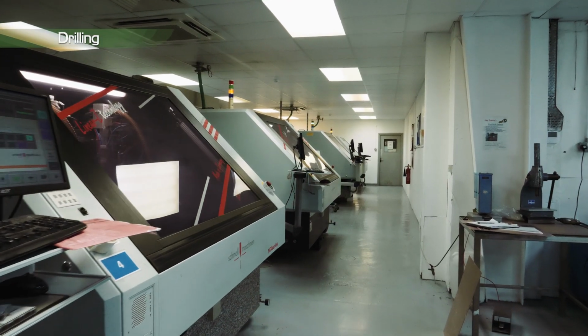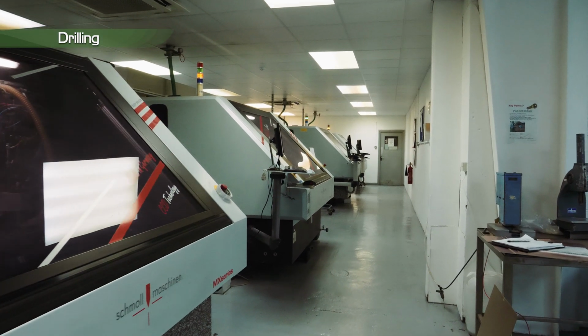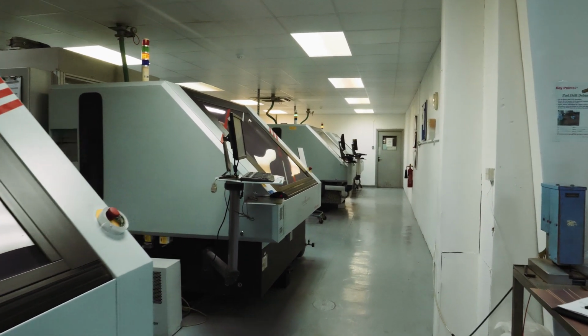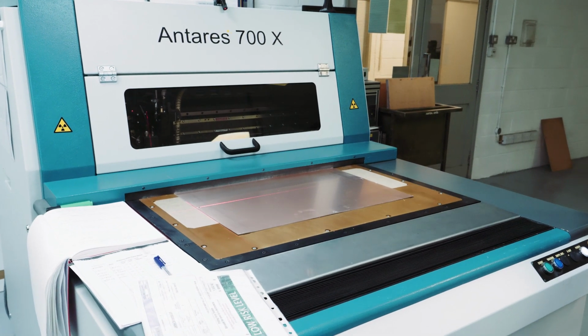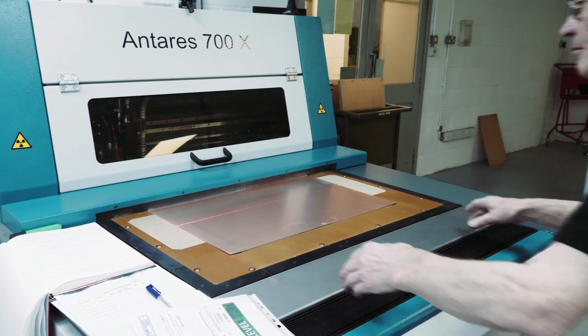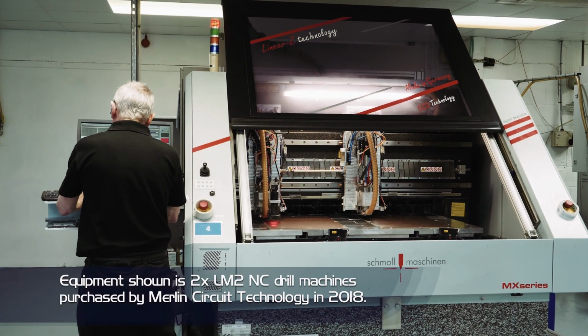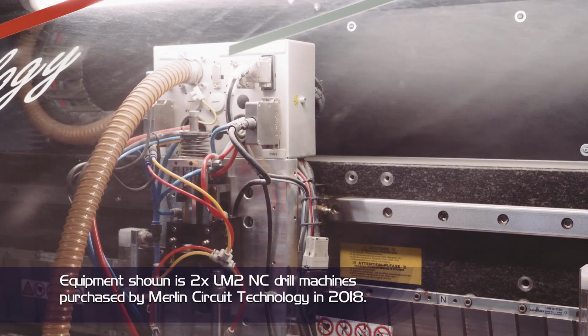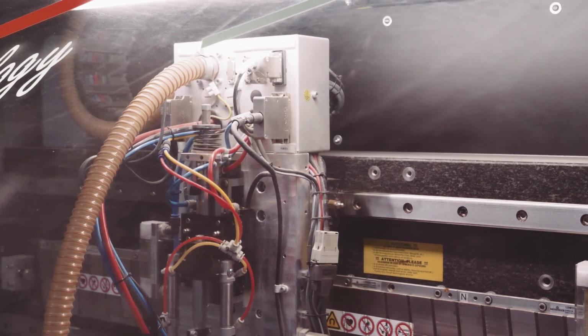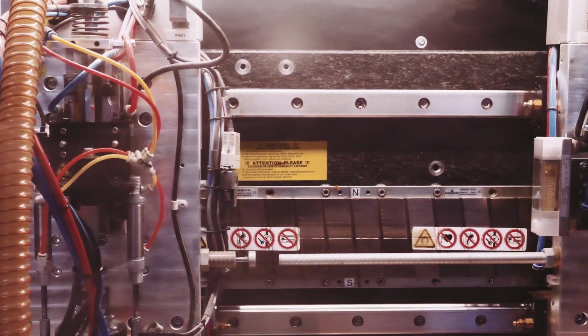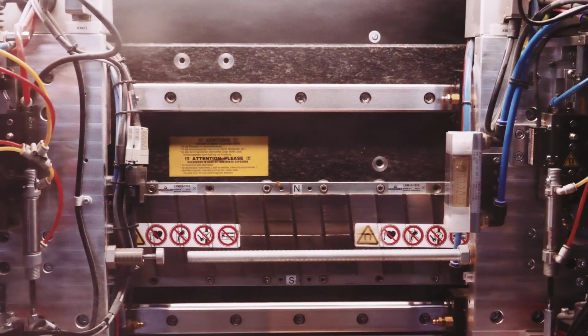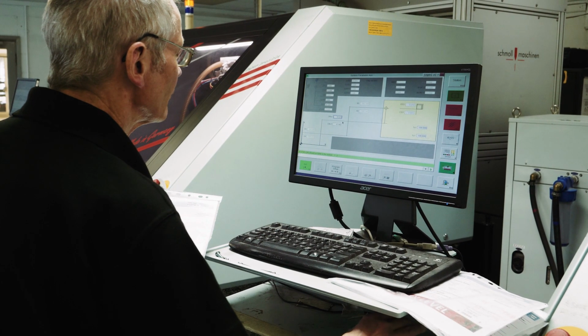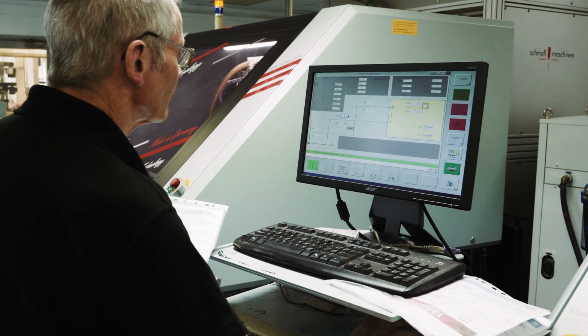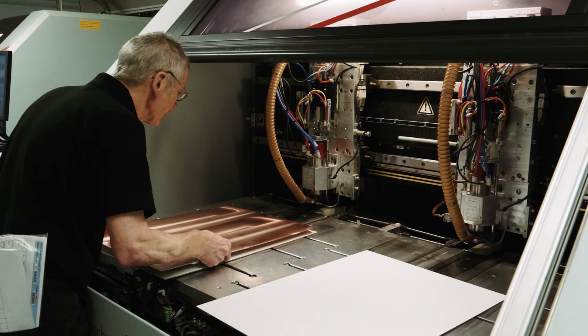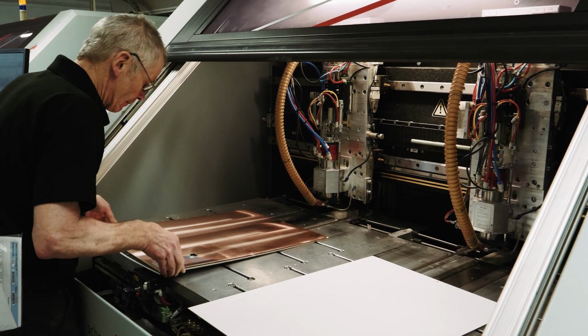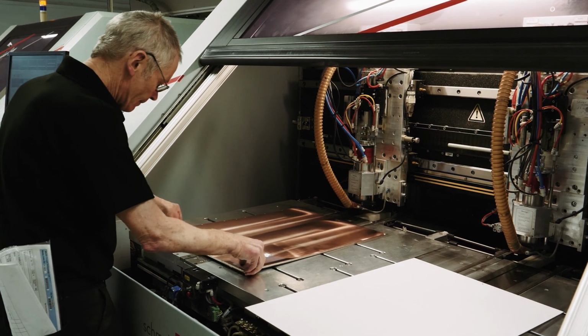At this stage, we drill the holes that will form the electrical connections between the layers of the PCB. The locations are determined by the customer's design to fit specific components. Drilled hole sizes are usually 100 micrometers larger than the finished hole sizes to allow for the copper plating process. The drill machine can detect when the drill piece has a broken or chipped drill, and when the drill becomes blunt, can automatically change to a new drill. Panels can be drilled up to 4 high depending on board thickness, drill size, and copper content.